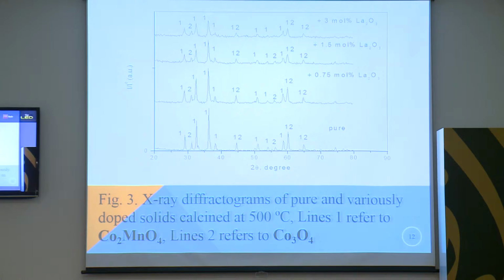Increasing the calcination temperature to 500 for all solids led to increasing the peak area of the main peaks, Co2MnO4 and Co3O4, as in this figure. Also, the presence of lanthanum oxide doesn't give any peaks in these curves. This refers to the lanthanum in these solids acting as a dopant, and there are no reflection lines referring to it. Also, it is clear from these figures that increasing the dopant concentration from 0.75 to 3 mole percent of lanthanum oxide led to decreasing the peak area of the main phases, Co2MnO4 and Co3O4.